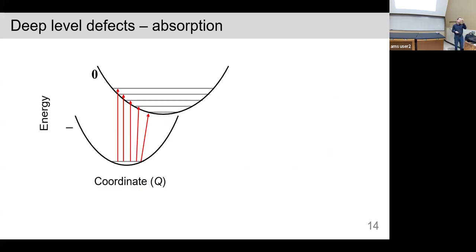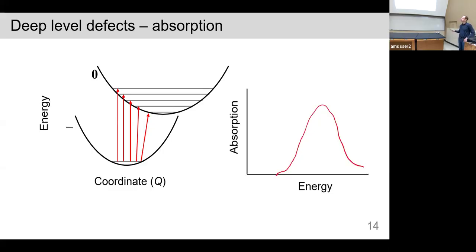And that has a few implications. Since we're talking about how crystals look, we have what's called a coordinate diagram, which just means the position of the defect, essentially. Let's say we have a negatively charged defect. If you move that defect this way or that way, it's like a harmonic oscillator potential. So it has its equilibrium position. Then if you excite an electron to an excited state, now the thing is in a neutral state because you pop the electron off. But you can excite it into various vibrational sublevels, n equals 0, 1, 2, 3, 4. And so these are all possible transitions. The short story is it tends to broaden the absorption peak. Instead of having a sharp line, now we have this big, broad, vibrationally broadened peak because of all these vibrational modes that it can go into. So you have a whole range of energies.